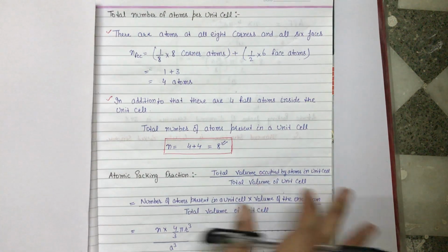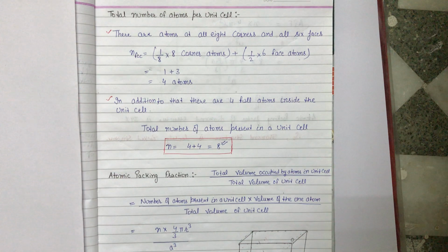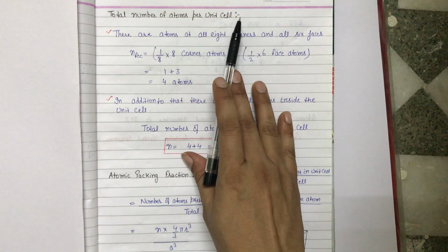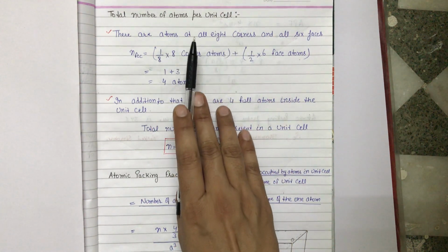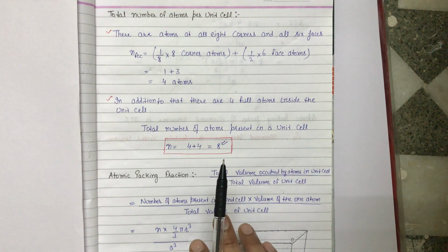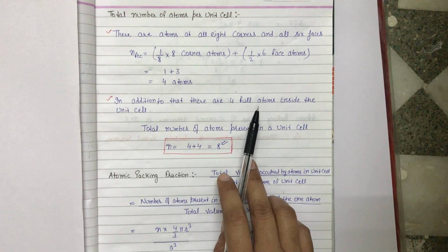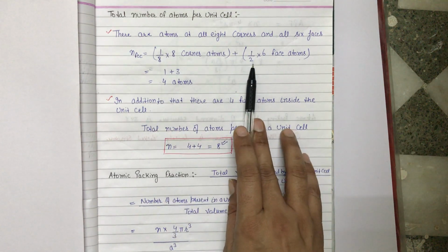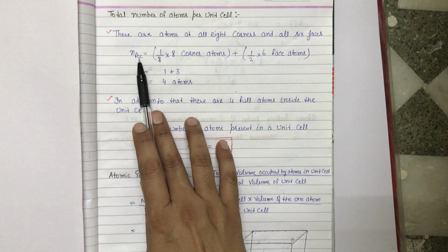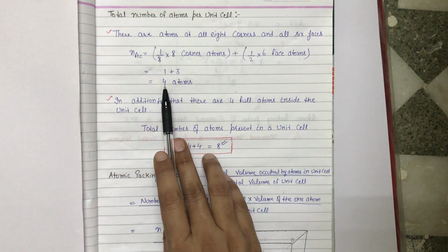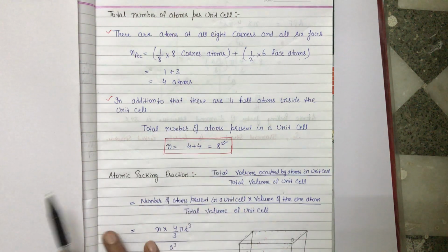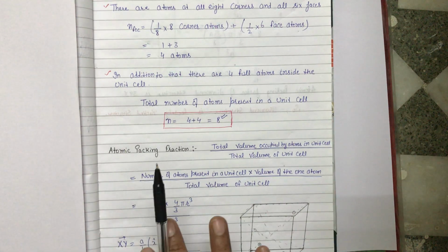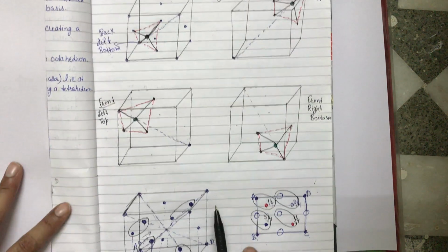Now discuss the characteristics of this diamond crystal. So the total number of atoms per unit cell in the diamond structure: 8 carbon atoms are placed at 8 corners and also at the 6 faces. So 8 corners will contribute 1/8 and 6 faces contribute 1/2. So this face centered structure contributes 4 atoms to the unit cell, and also 4 atoms are placed along the body diagonal, which are completely inside that particular unit cell. You can mark these 4 atoms.